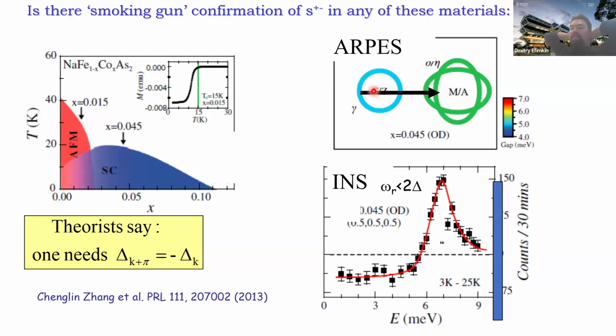But it will reduce the critical temperature. So if you eliminate disorder, in this case the temperature is supposed to dramatically grow. Yeah, supposed to rise. That is true. I actually don't know whether there has been any systematic study on this. The problem is that in the oxides, the main issue is that nobody really knows the number up to, you know, 5%. Nobody can tell you how many oxygen are inside. So in this regard, it's not the best system to study the disorder.